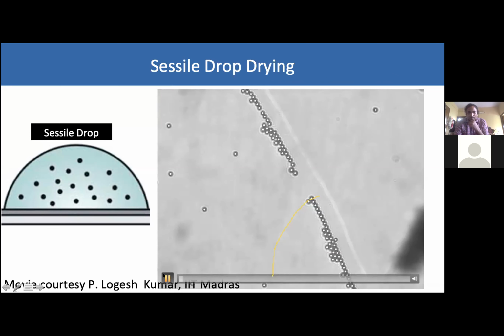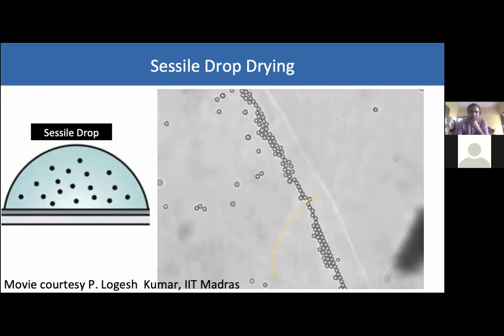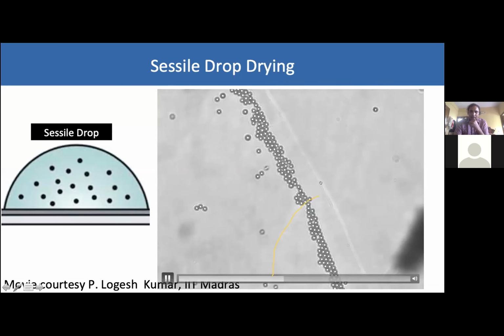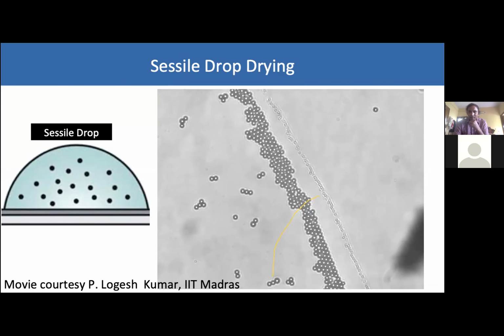So this is a more zoomed in version wherein we are looking at the edge of the droplet, that's here, and you will see that the particles are coming and depositing at the edge. These were the particles that were initially well dispersed in the fluid, and as the evaporation proceeds, the particles come to the edge and then keep on depositing there.